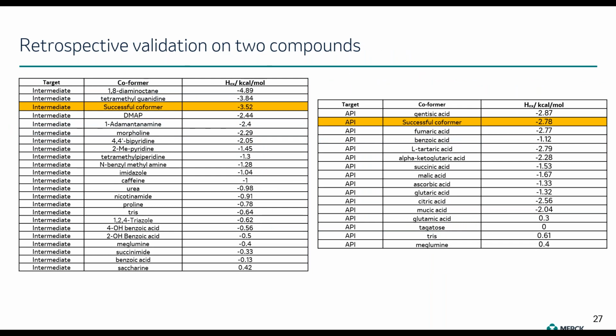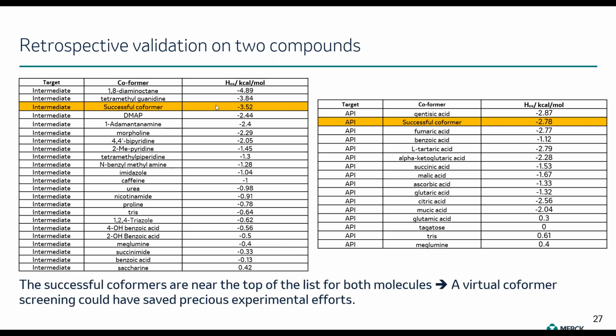Here I'm going to show you a retrospective validation that we did on two compounds. One is an intermediate and one is an API. For both of these compounds, all these coformers were experimentally screened before we did the virtual assessment. And in both cases, only one successful coformer existed. And in both cases, the retrospective modeling identified it near the top of the list. So what this means in practice is that if we had applied the virtual method before, we could have gotten the same hit, performing a significantly reduced number of experiments. And so a lot of time and resources would have been saved on performing co-crystallization experiments that ended up to be unsuccessful.